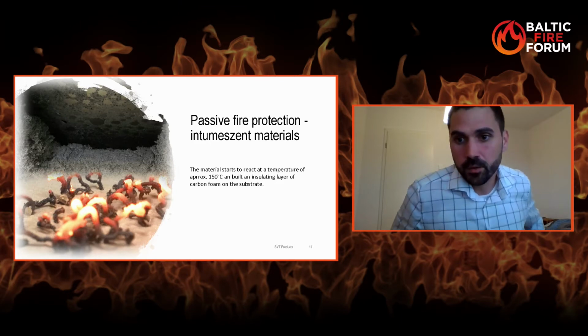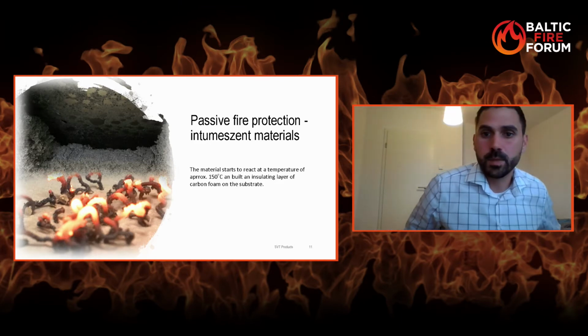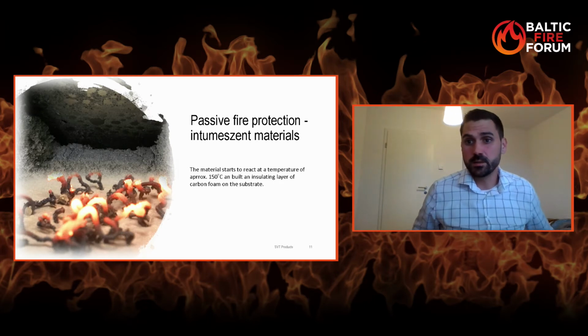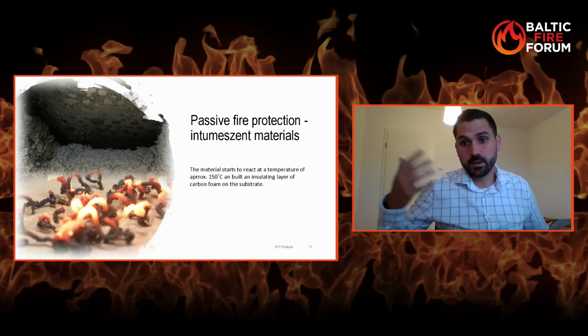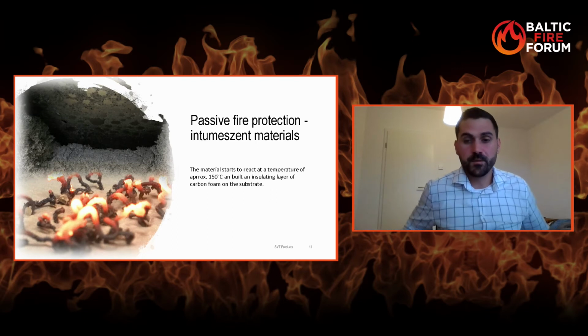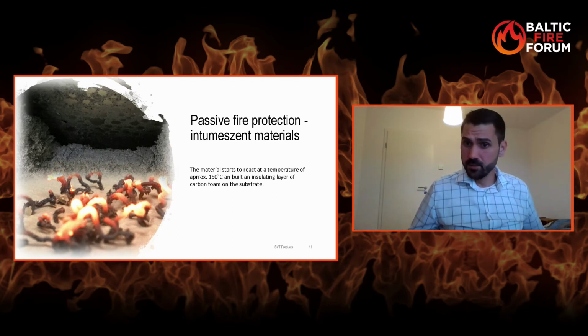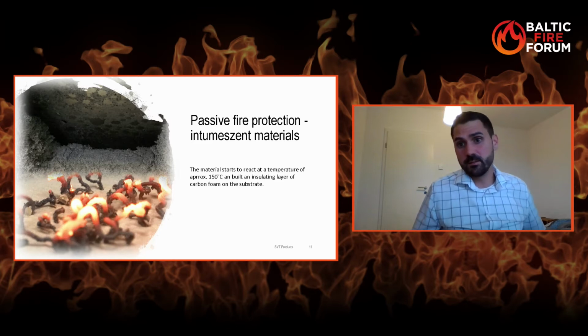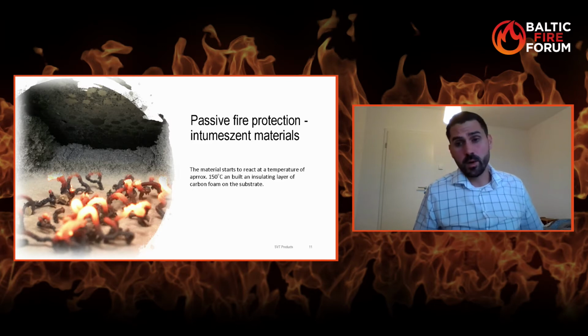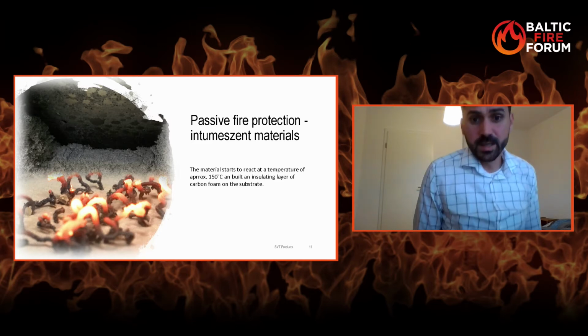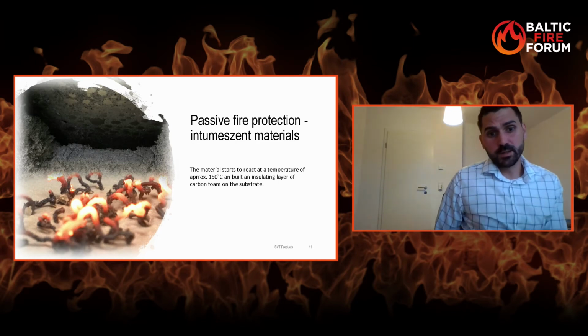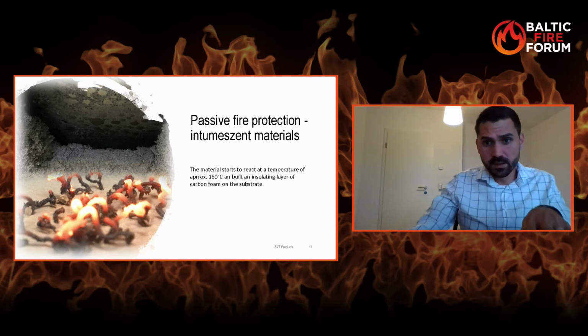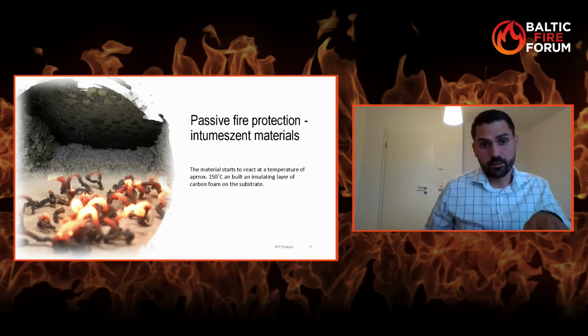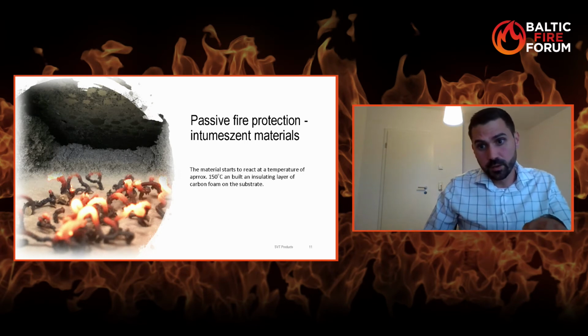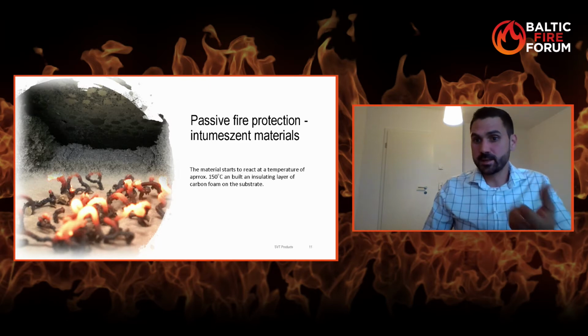I don't know if you really know what passive fire protection is and what kind of material we use. A lot of our materials are intumescent materials. Intumescent means the material starts to react at a temperature of approximately 150 degrees and builds an insulating layer of carbon foam. As you can see below, the reaction temperature starts, and the material builds a foam that insulates the substrate.